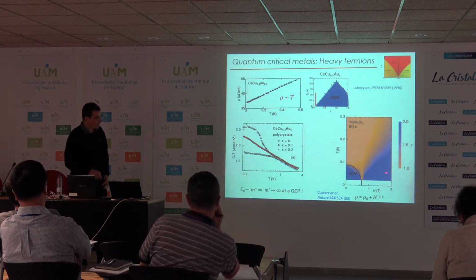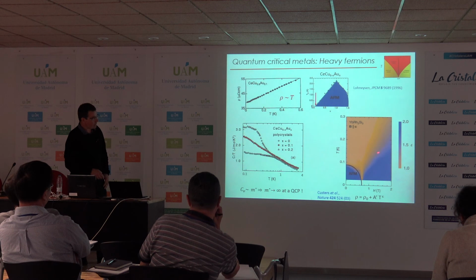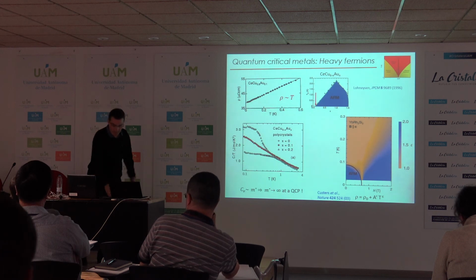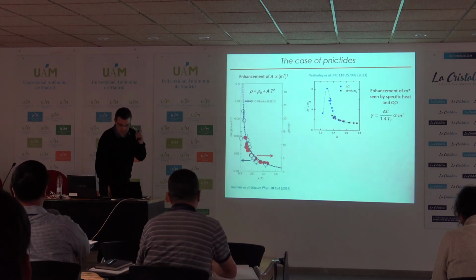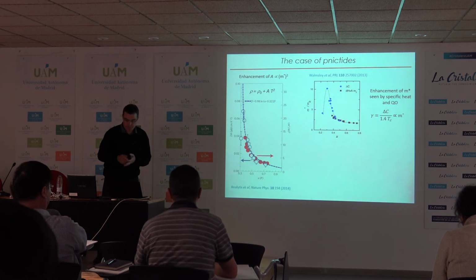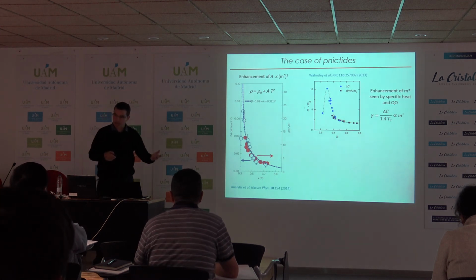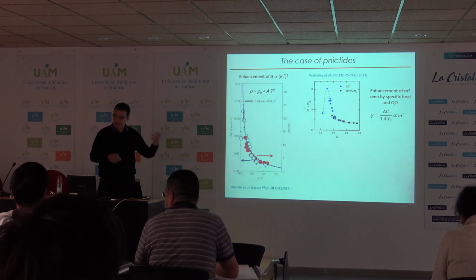And if you are above the quantum critical point, there is a fan, so you will see a linear resistivity at high temperature, but at some point, what we call the coherence temperature, there is a crossover to a T-square resistivity. So you can measure the A coefficient of the resistivity, which is linked to the m star squared.